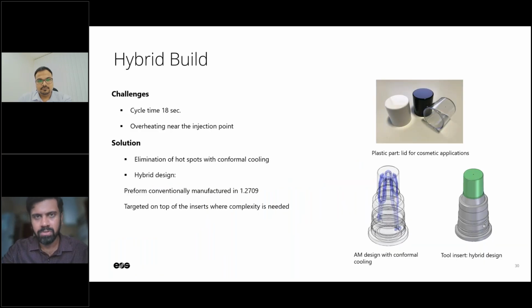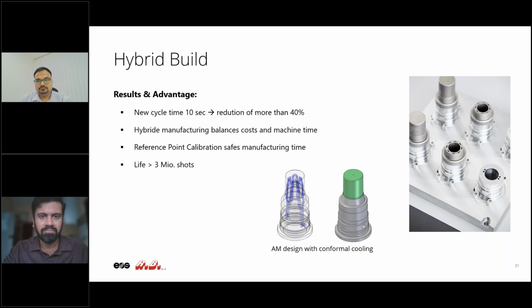Another interesting tool that we also offer, especially for tooling customers, is hybrid build. Sometimes when you see a part, it just has straight drills and does not require complex channels until the very top end. Probably you can have that part already machined, fixed onto the machine, and then print only the conformal cooling segment. Right. So this is one such customer of ours, and they were able to reduce from 18 seconds to 10 seconds on injection molding. Right. And when we fix it onto the machine, it should also be referenced properly. For that we offer a tool called reference point calibration, where you can quickly reference these parts to start the build.